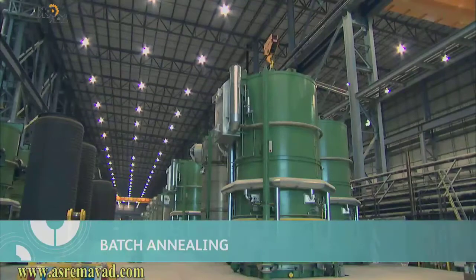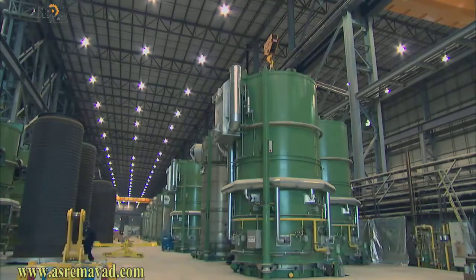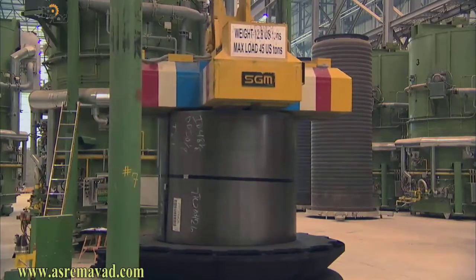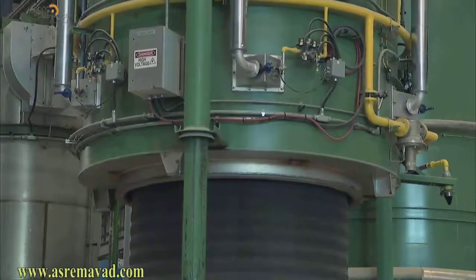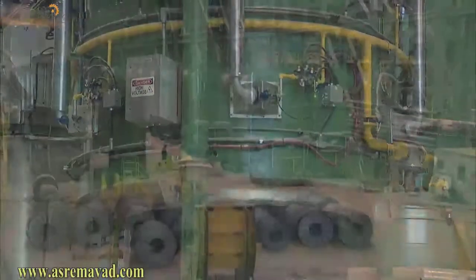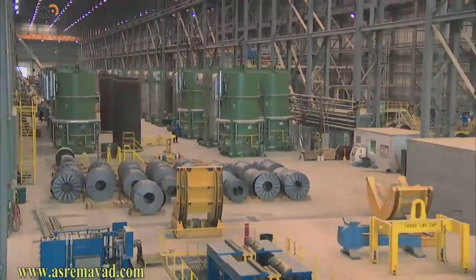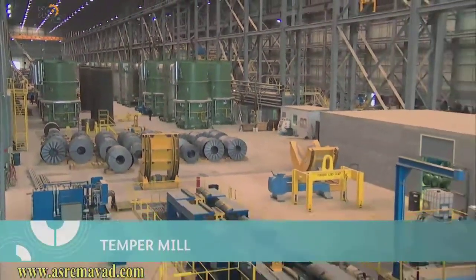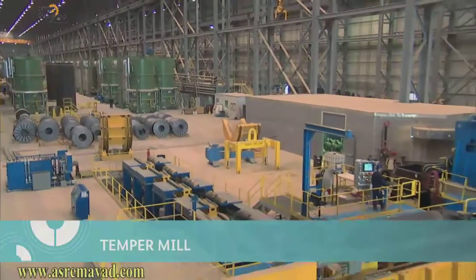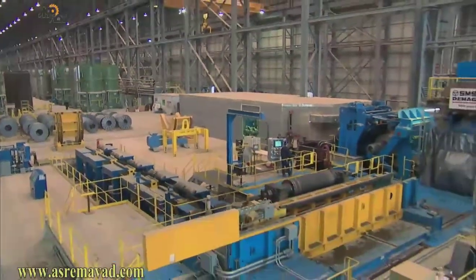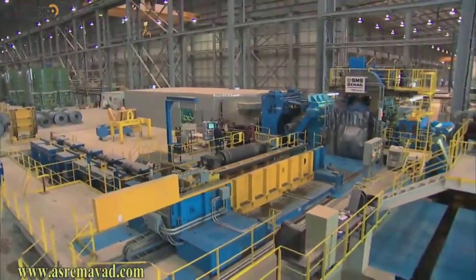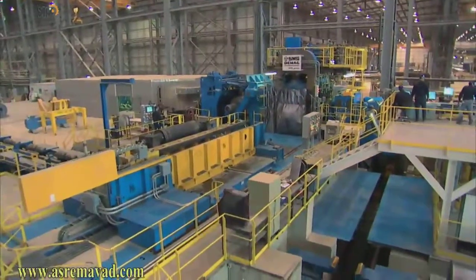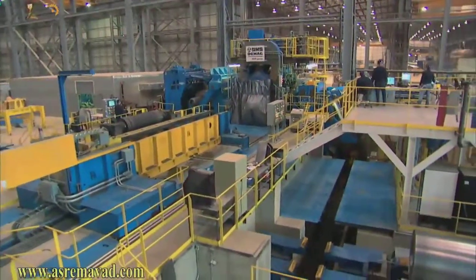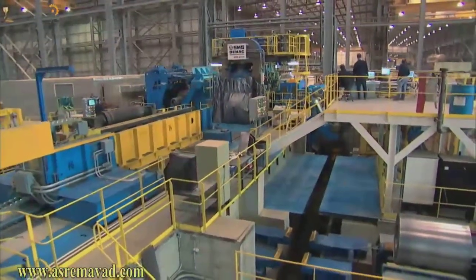Batch annealing restores ductility to the steel for improved stamping and forming. Coils are stacked and annealed by heating in hydrogen atmosphere furnaces. After about 3 days in the furnaces, the coil moves to the temper mill, where the customer's specifications for surface finish and mechanical properties are met. This fully processed cold roll is used in lawn and garden products, appliances, tubing, and shelving.